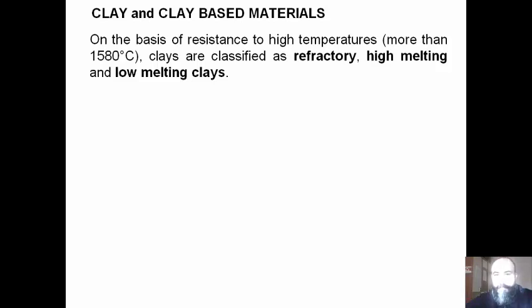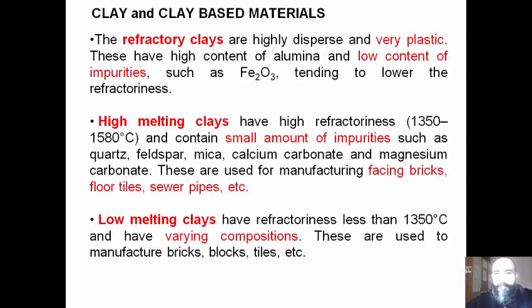The refractory clays are highly dispersed and very plastic. These have a high content of alumina and low content of impurities such as ferric oxide, which tend to lower the refractoriness. High melting clays have high refractoriness of 1350 to 1580 degrees Celsius and contain small amounts of impurities such as quartz, feldspar, mica, calcium carbonate, and magnesium carbonate.